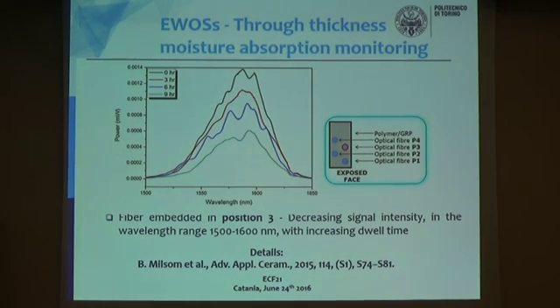So, some results. We have embedded fibers into those samples, and we made different tests. Here you have an example of a sample where fibers are embedded at different positions through the thickness of the sample. And if you take, for example, one fiber in the middle, you can see that there is the transmitted signal that is dropping as the water diffuses into the polymer resin, into the vinyl ester resin. There are some details in a published paper. And by putting those fibers at different positions, it's possible to extract the rate of diffusion.